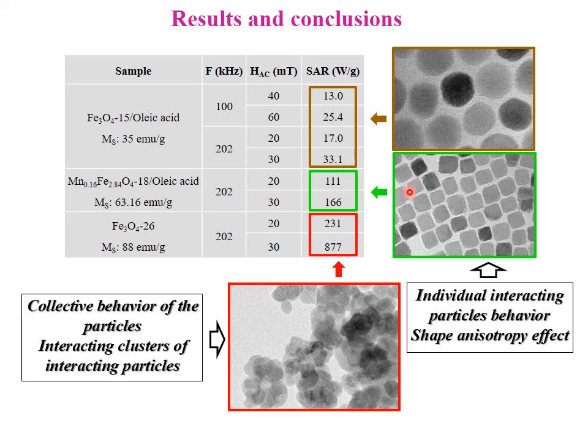particles, the collective behavior is probably responsible for the high relative SAR values. This collective behavior of the individual particles with the anisotropy axes aligned can increase the anisotropy of the system and the efficiency of the heating. This collective behavior can be understood as a result of the interacting cluster of interacting particles.